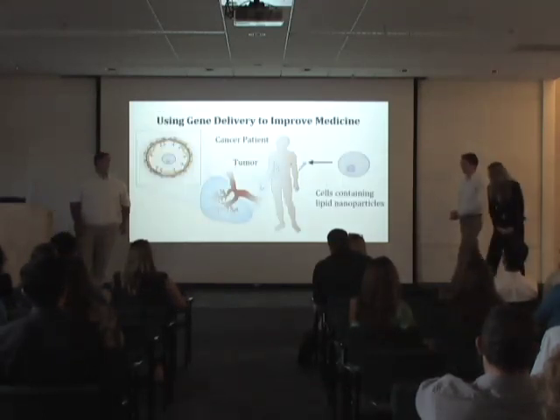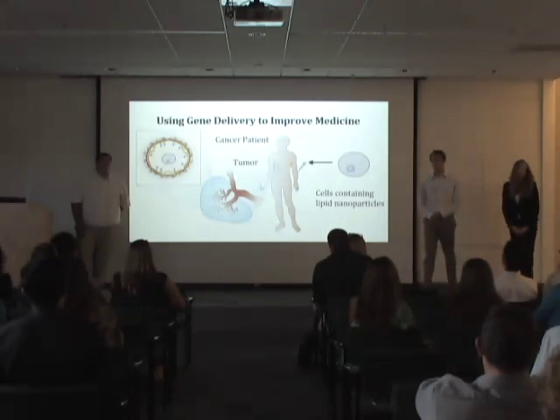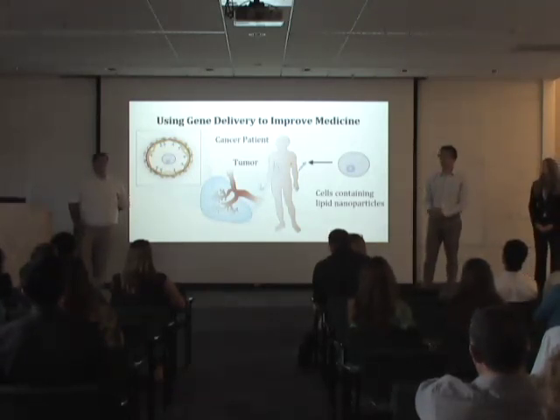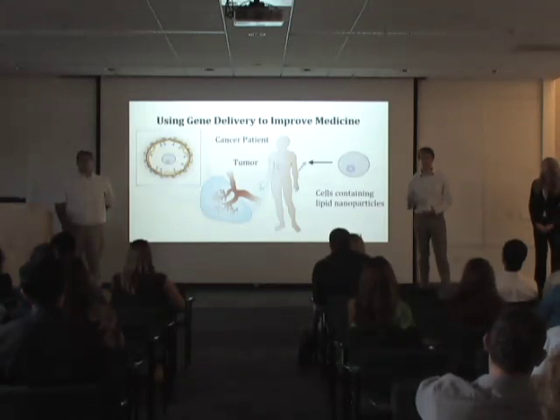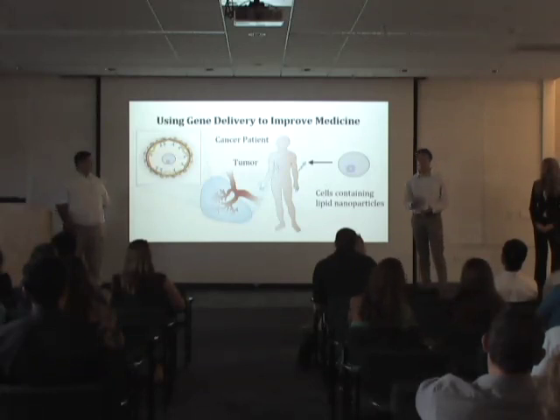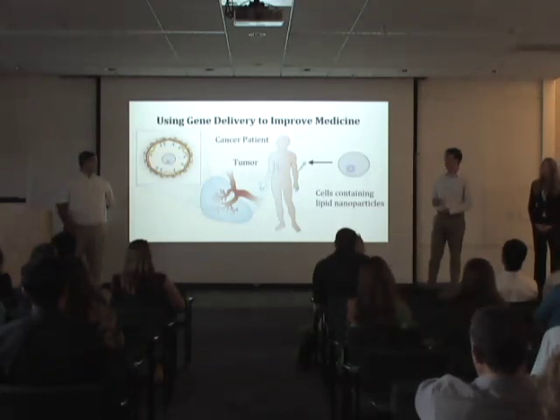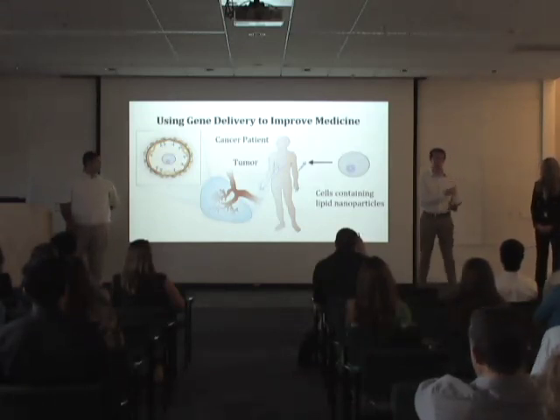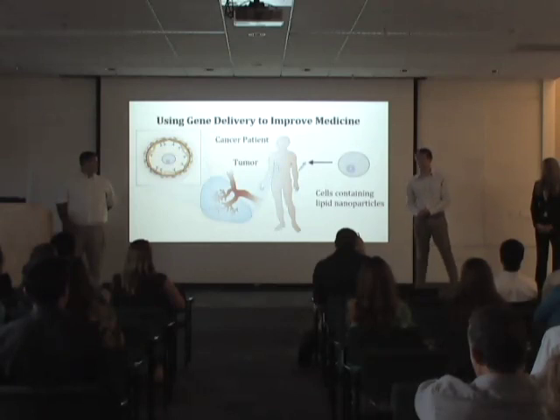As we had hoped, our lipid PEG-RGD nanoparticle was able to restore the efficiency of the neutral lipid by itself when using a charge ratio of 20. It should also be noted that gene expression increased, regardless of charge ratio, when we used the lipid PEG-RGD nanoparticle.